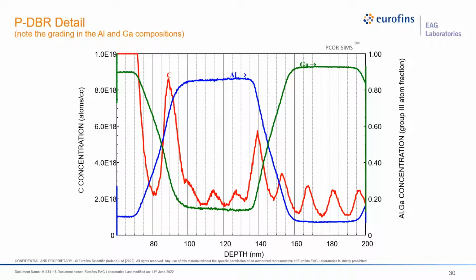We are confident that the placement of the carbon doping spike is correct because all of the profiles were acquired in the same analysis. And note how the low-level carbon doping spikes may originate from a non-uniformity in doping while the wafer was rotated during growth.